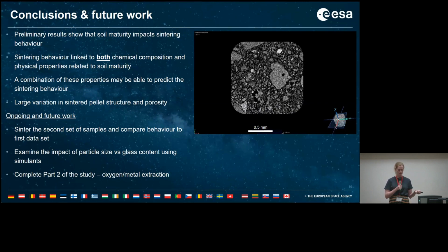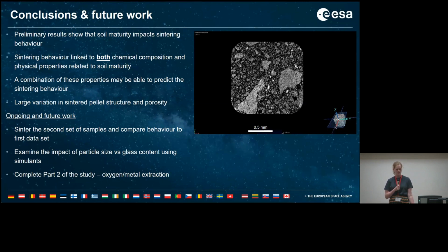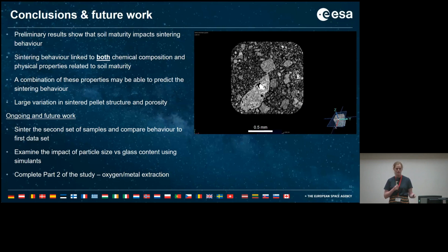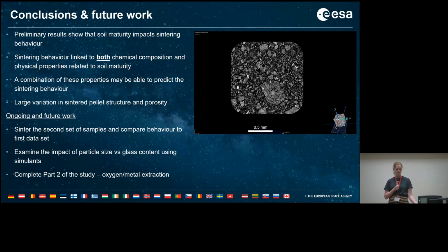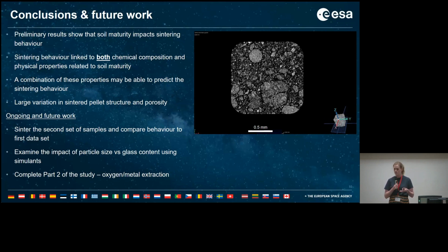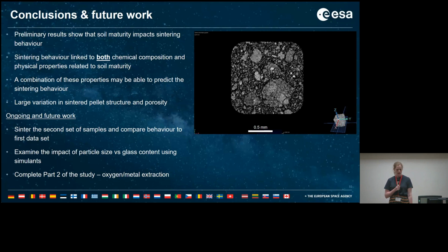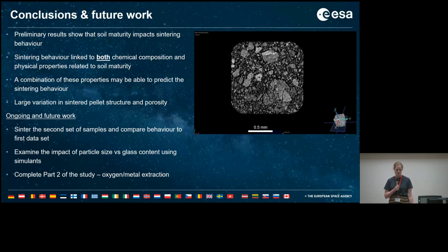So the preliminary results show that the soil maturity impacts sintering behavior, and that the behavior can be linked to both chemical composition and the physical properties relating to soil maturity. And so we might be able to predict the behavior using a combination of these things. We see a large variation in the sintered pellet structure.